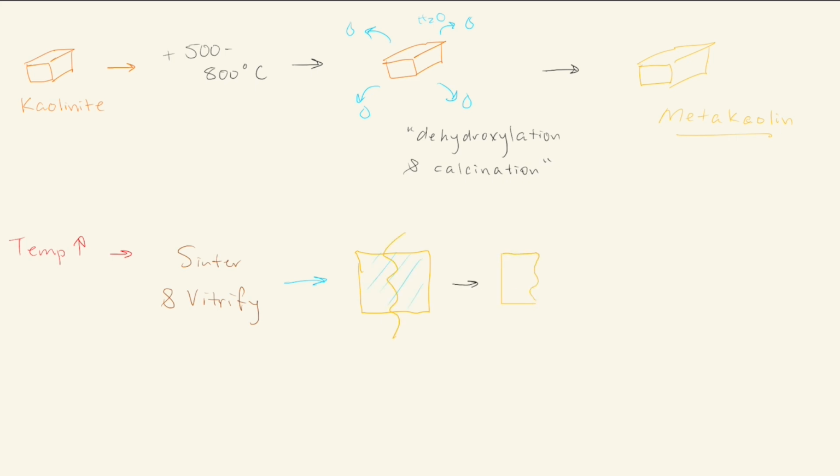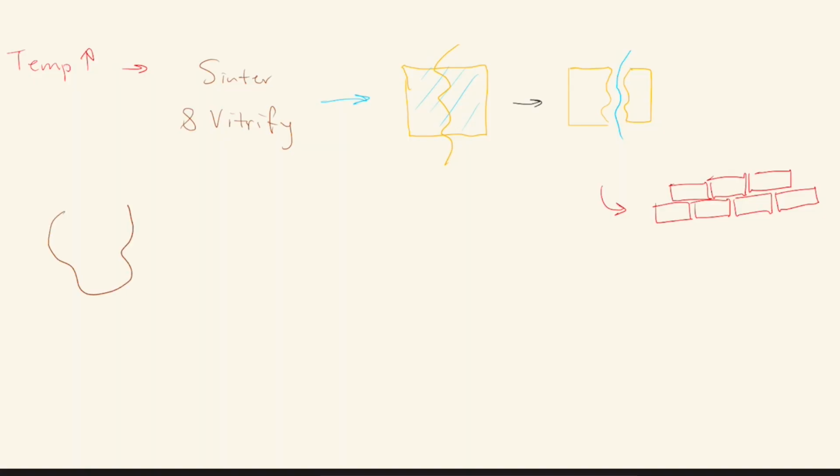You can picture this change by imagining breaking a piece and seeing a clean break where you could fit the pieces together perfectly. These changes harden the clay, make it less porous, and give it the durability that's essential for pottery and bricks. If heated too much, the process can be overdone, which can cause bloat and deformation from expanding gas bubbles. In pottery, natural clays like ball clay are often mixed with kaolinite in order to provide a good balance between plasticity and stability when fired in the kiln.